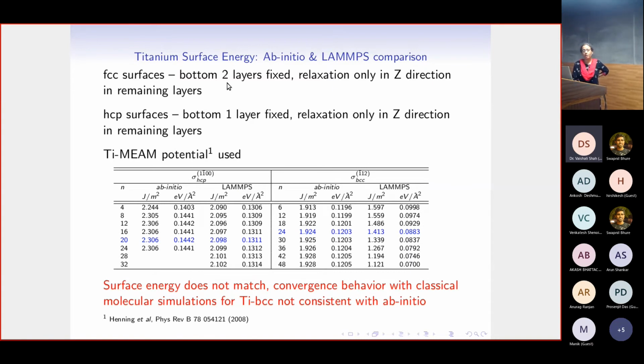So to do the surface simulations, we fixed the bottom 2 layers, and for the HCP surfaces, we fixed the bottom 1 layer, and for all other layers, we are allowing them to relax completely in the Z direction. We are not allowing them to relax in the X and Y direction because we are mimicking the bulk. So in the X and Y, they are not allowed to relax. So if we look at now, this n tells you the number of layers that we have used in this simulation, and this is the energy that we obtain for each layer. So each number there, let me say if I have 4 layers, then that is the energy. If I have 24 layers, then that is the surface energy.